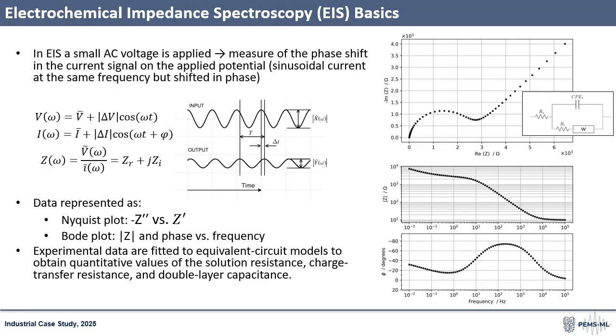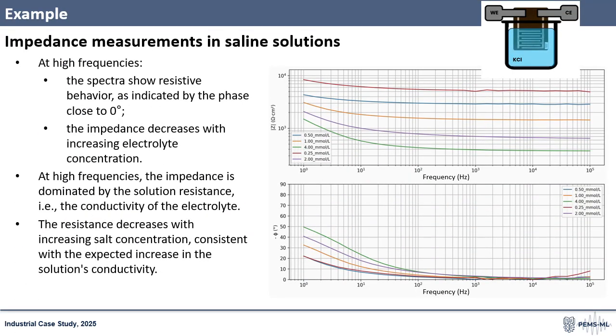The data are interpreted using an equivalent electrical circuit, composed of elements like solution resistance, Rs, double-layer capacitance, CDL, and charge transfer resistance, RCT. In this example, we see that at high frequencies, increasing salt concentration decreases the Z, i.e., the resistance, because the solution becomes more conductive. At high frequencies, the response is almost purely resistive, while at lower frequencies, capacitive effects emerge. This simple case clearly shows how EIS can detect even subtle changes in the surrounding environment.